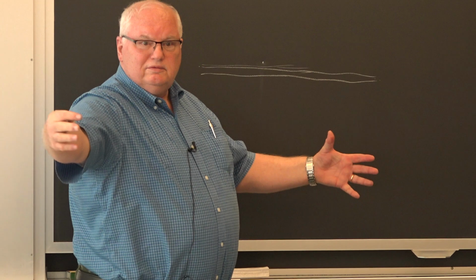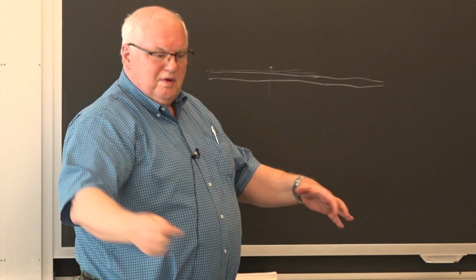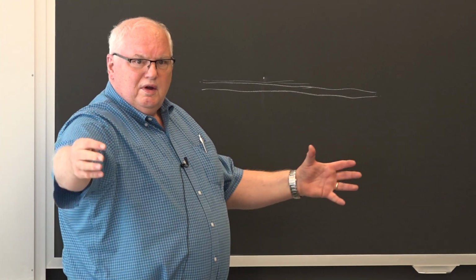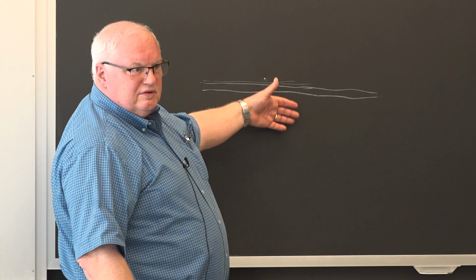Corning worked on something that everyone said was impossible. Do you know how they make optical fibers? Anybody know? They draw it, but it's actually sort of a clean room environment of making glass, and they start with a very, very pure quartz fiber that they've drawn down, and then they flame vapor deposit layers on this thing as it's rotating. They'll end up making something that's 4 or 5 inches in diameter and 3 feet long. And as they do it, they can functionally grade the composition of the glass.